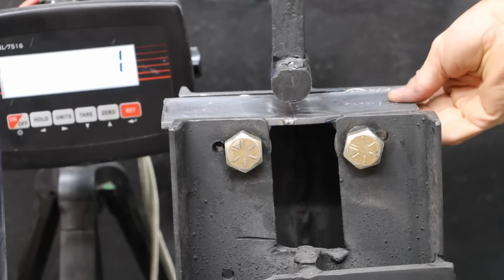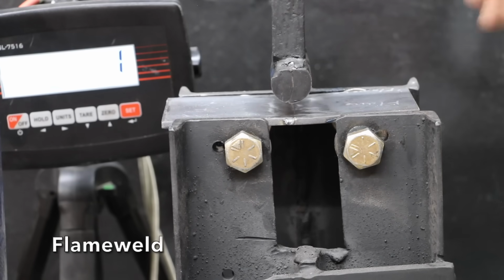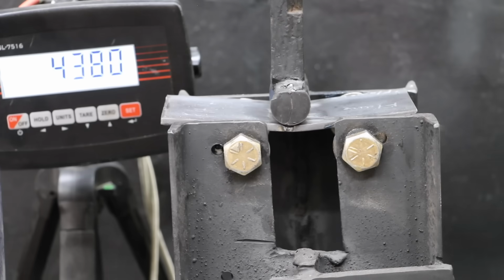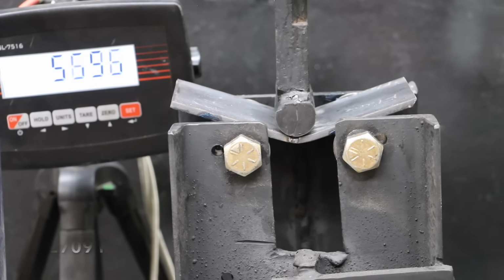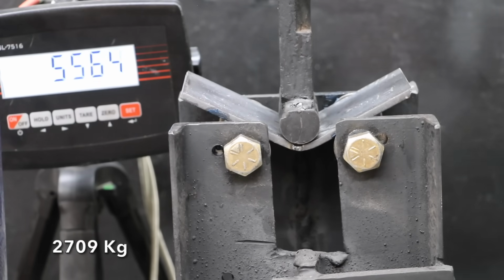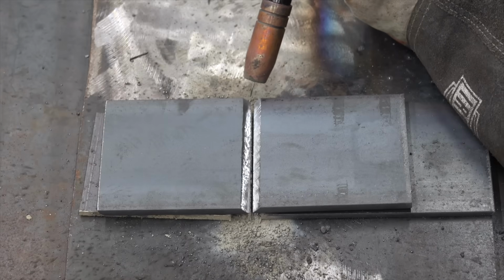I put together a tester to test the strength of the welds. The scale will measure the amount of force it takes to break the test piece. And Virgil is right about the cap weld. And the weld finally broke at 5,972 pounds. And the Chicago Electric's wire speed is a little bit more consistent than the Flameweld's.